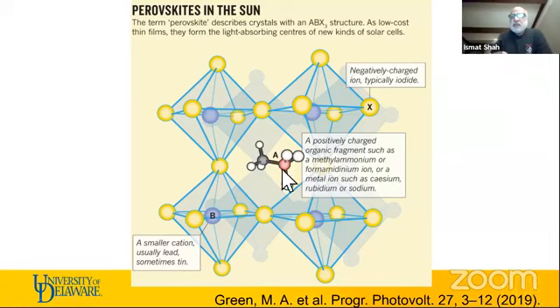Some of these, particularly this A, for example, or B especially, start to migrate. As soon as it starts to migrate, the structure goes away and you don't have the efficiency. It comes down from the best 17% to maybe as low as 3 to 4%. And it happens very fast in a high temperature situation. High temperature means a rooftop in Pakistan, for example.